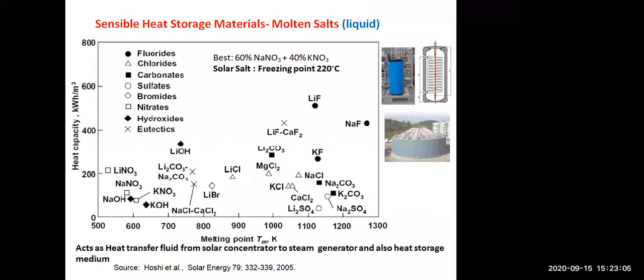Then liquid storage media. Among the liquids, water is the best and the most commonly used storage medium at a low temperature range. It may be from 25 to 90 degrees Celsius. After 90 degrees Celsius, it reaches the saturation temperature of water. So other substitutes for water are petroleum-based oils, liquid sodium, and molten salt, etc.